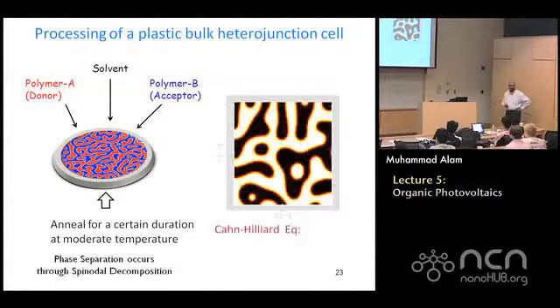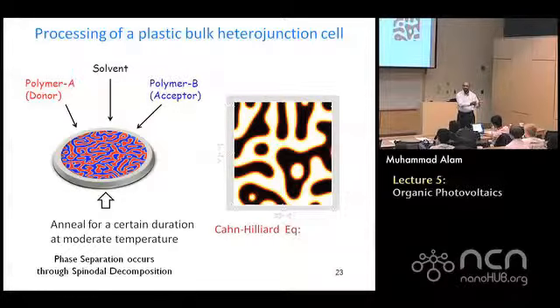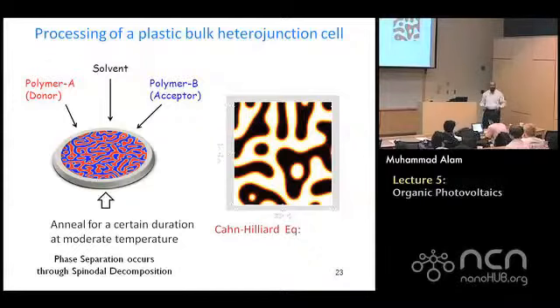So this is going to get phase segregated. Did you notice two things? One is that as time progressed, the black and the white phase volume didn't change. If you started with 1 kilogram of polymer A and 1 kilogram of polymer B, none of them evaporated. So at the end you still have 1 kilogram of polymer A and 1 kilogram of polymer B. That's a very important statement because nothing evaporated.